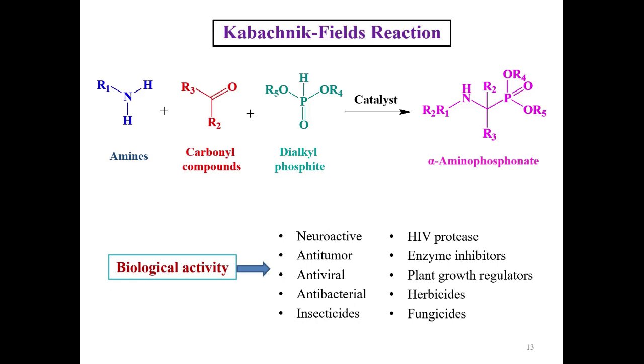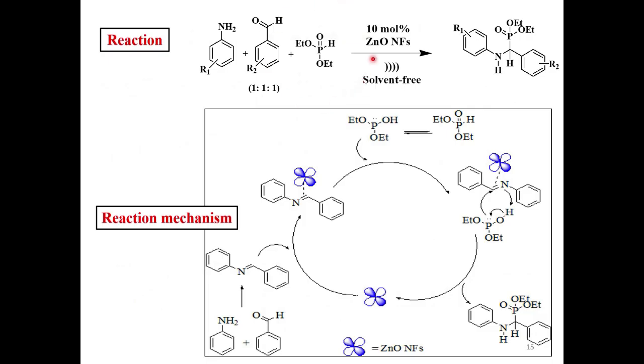Carbonyl compound plus dialkyl phosphite react in the presence of 10 mole percent of zinc oxide nanoflowers as a catalyst. In the presence of the ultrasound cavitation technique in solvent-free conditions, it forms the alpha-aminophosphonate. This is the complete mechanism: when the phosphonate group forms the complex, the nanoflowers attach to the double bond of the imine, and then the reaction proceeds. This attack is from the external side, therefore the separation of the nanoflowers becomes very easy, and once the reaction is completed, we separate out and regenerate the catalyst and utilize it for the next cycle.